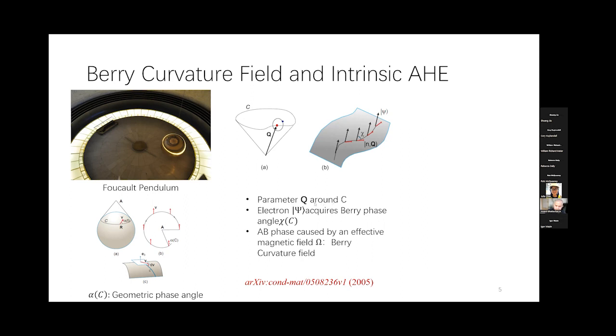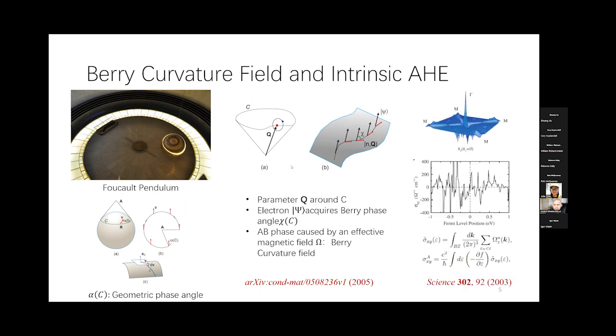So this effective magnetic field will act on the electrons' motion and give them an anomalous velocity. That's the reason we have an intrinsic anomalous Hall resistance or conductivity. So basically, we can use a first principles band structure calculation to calculate the Berry curvature field, and then we obtain the anomalous Hall conductivity and use that to compare with the experimental result.